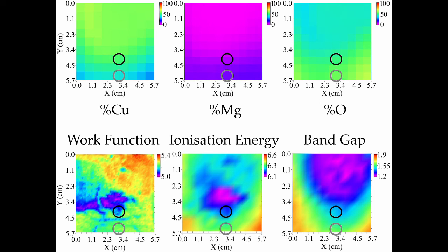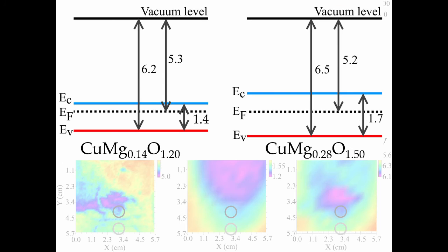From this information, local band diagrams can be drawn at each point of the maps to provide a useful and transferable summary of the electronic properties, as demonstrated for two distinct chemical compositions, indicated here by the black and the grey circles. The black one is shown on the left, the grey band diagram shown on the right. Two things are of particular interest. The left band diagram has a band gap of 1.4 eV, which is considered ideal for the light absorbing layer in solar cells, as it provides a balance of the number of photons that can be captured and the energy